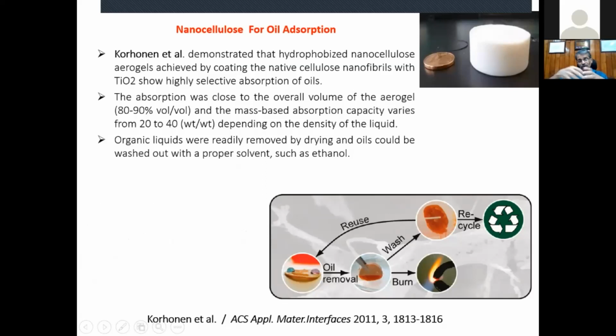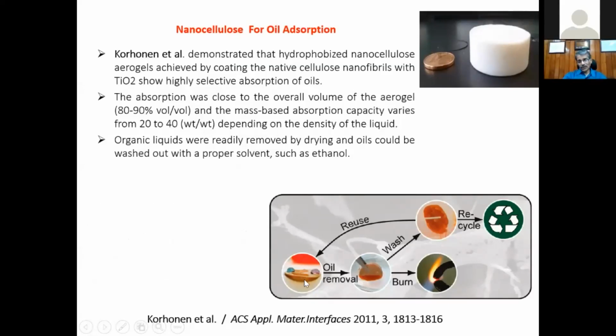Once you do that, the oil could be absorbed by the aerogel. You can see this red is the oil. You sprinkle in seawater, the oil in seawater could be absorbed by this nanocellulose. But water cannot get in because you made the surface hydrophobic. And once oil is absorbed, you can recycle the oil or you can burn it. This is a very good technology by which